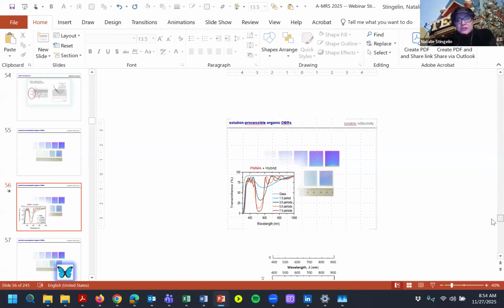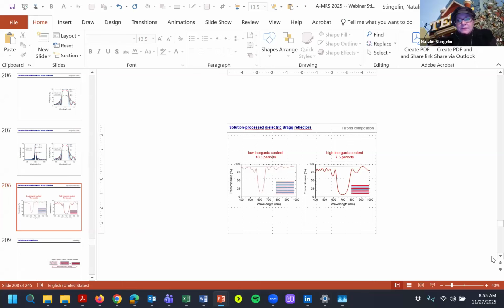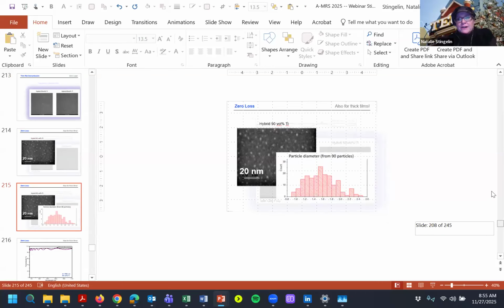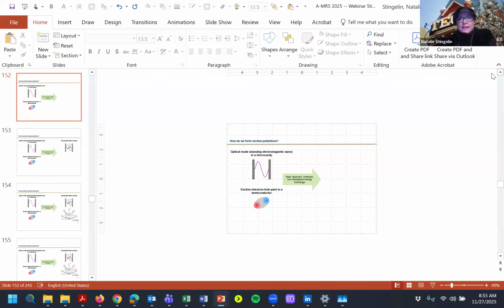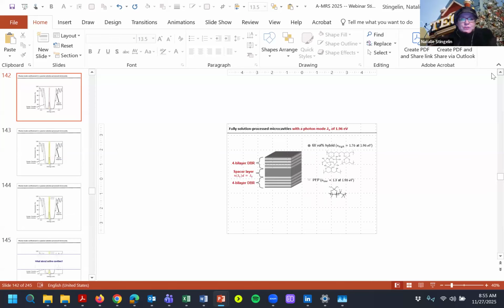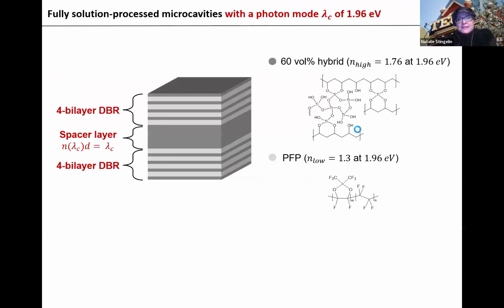And also when you look at the polyvinyl alcohol hybrid, people would usually possibly worry more about the hybrid than the fluorinated polymer. But the hybrid material with polyvinyl alcohol is actually very stable. Usually, polyvinyl alcohol would definitely degrade in a Saudi desert. The reason is usually that the hydroxyls are attacked, and therefore you get double bonds again, leading to yellowing. But in our hybrid, we actually consume a lot of the alcohols, so they will be very difficult to get to. And therefore, we know the hybrid is definitely far more stable than the polyvinyl alcohol by itself.